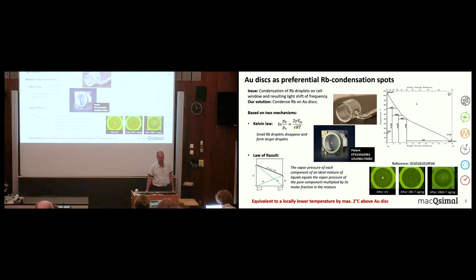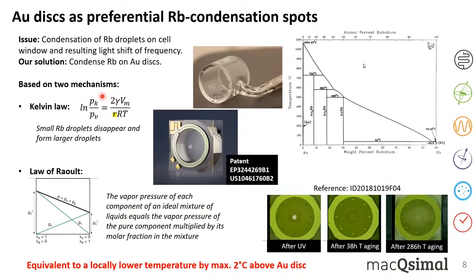So we thought if we can take advantage of this behavior, that gold and rubidium, they like each other very much, we introduced these gold discs inside the vapor cell. So this works very well, and it is based on two different mechanisms. On the one side, we have the Kelvin law. We don't want to go into detail of the formula, but it says that the vapor pressure of a droplet compared to the vapor pressure of a flat surface is inversely proportional to the radius of curvature of the droplet. So this means that small droplets have a higher vapor pressure than bigger droplets, and they will disappear in time. They will form larger droplets, and all the small droplets will disappear.